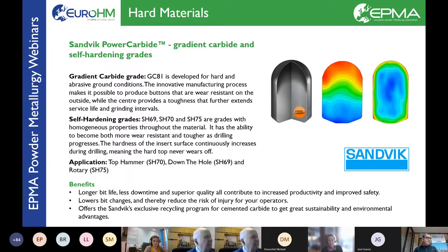The other one that is to the right is the hardness profile of that. That grade is specially made for work hardening. And in this case, the more you hit, the harder the exposure you put it out to, the harder the response will be. So it becomes both harder and more wear resistant as the drilling progresses. The top one, I should mention also again, the GC81, it's extremely good in conditions with a lot of quartz in the rock, because it has a very low fraction of binder in the outer part